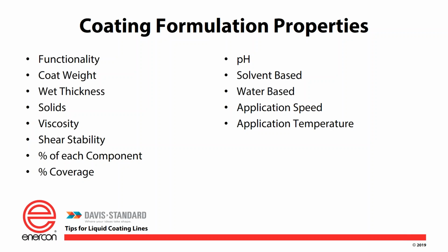You'll find, let's go back to the silicones, 100% solid thermal silicone will carry usually less than 1,000 centipoise in viscosities. But when you start putting additives for controlled release agents, or you get into the UVs where you're putting in some initiators, those viscosities tend to climb. And on a smooth roll coater like the 5-roll, the higher the viscosity, the higher the coat weight generally tends to be. We need more shearing actions. By increasing temperatures on those particular coatings, heating the rolls up, heating the bath up, we could actually lower the viscosities and get you a lower coat weight. So that's where we're at with your application temperatures.